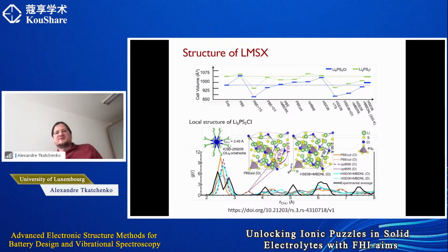Yeah, that's right. In the paper, we look very carefully as well at the phonons of these different frameworks, and we do find that the treatment of dispersion interactions has a very strong effect on the low-frequency phonons that dictate the lithium migration through the framework.